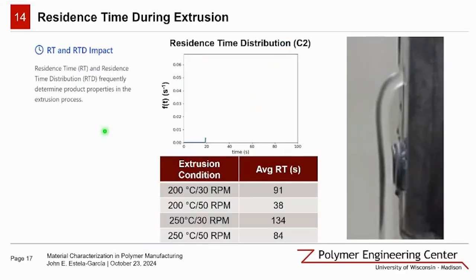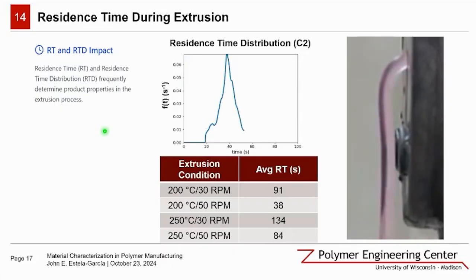So we turn here to a critical parameter, residence time. This factor plays a pivotal role in determining the final properties of our recycled materials. So we've here employed a colorimetric approach to visualize and quantify residence time. So there we go. By analyzing our data, we see some intriguing trends depending on our processing conditions. There's different residence times depending on the heat and screw speed that is being applied.